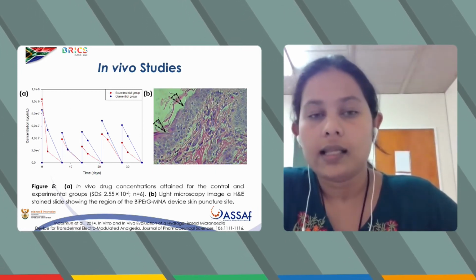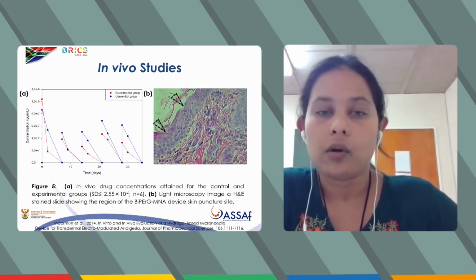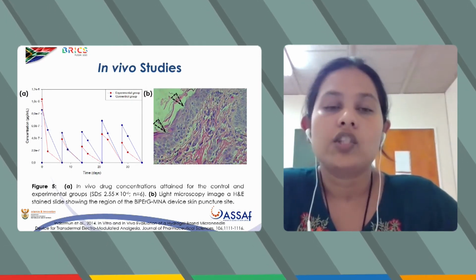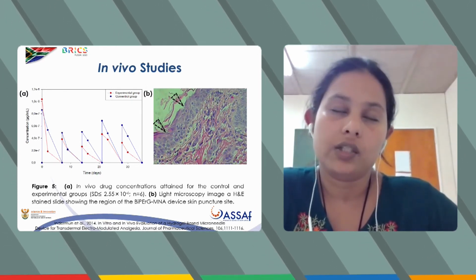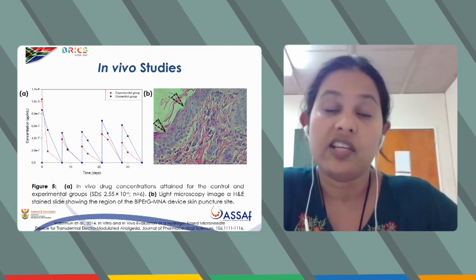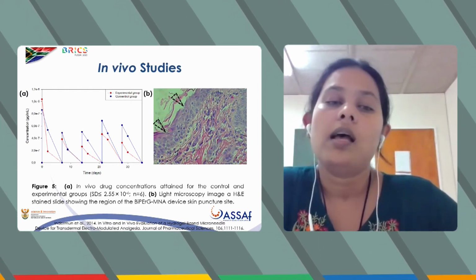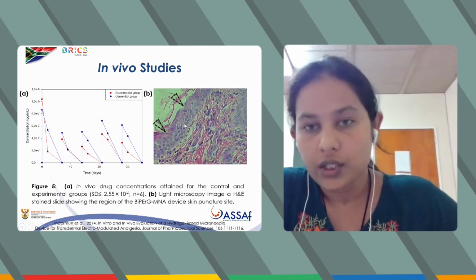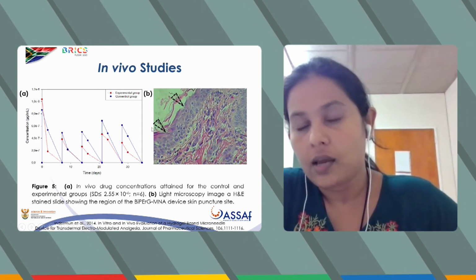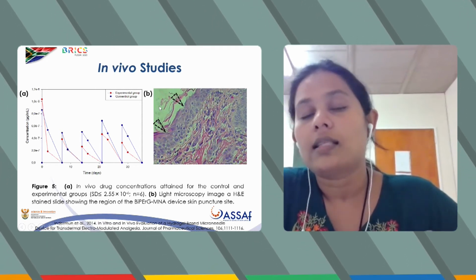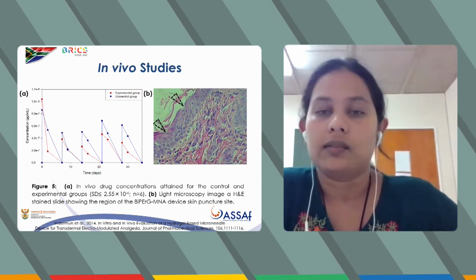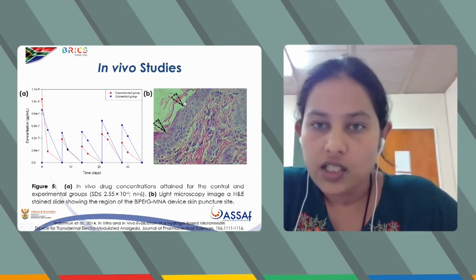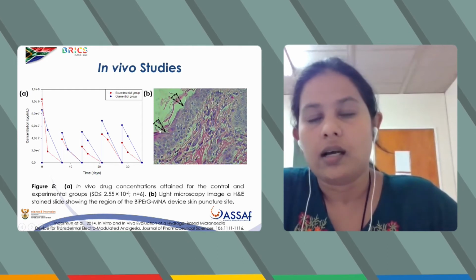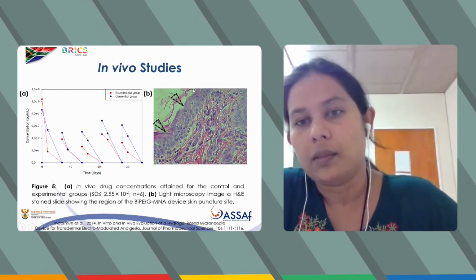Furthermore, in the study, there were no signs of discomfort or abnormal behavior seen in the rats, suggesting that all these doses did in fact reach systemic circulation, and thus reiterating the success of the study. There were only minor pathological changes observed in the epidermis of the skin sample that was exposed to the microneedle device. As you can see, there's just minor penetration shown from the microneedles.